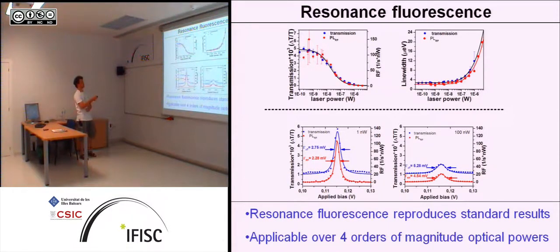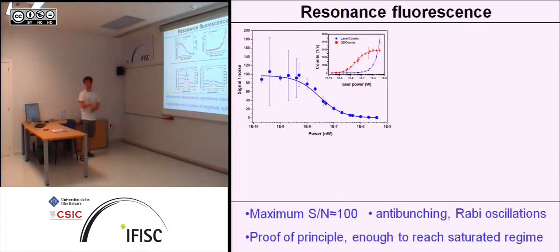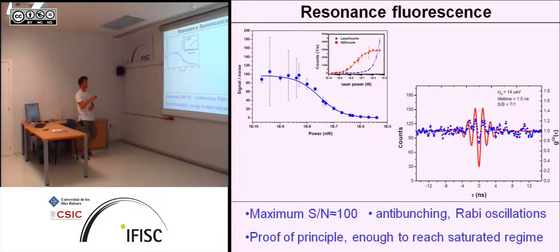And here we now use this resonance fluorescence to basically validate this technique, because the transmission spectroscopy has been around for a few years now, and it's been taken to be a valid experiment. And here we see that basically the resonance fluorescence perfectly, or almost perfectly, reproduces the features measured in standard resonance transmission spectroscopy. And here again 2 example scans showing the power broadening and the saturation of the transition. So this basically is a proof of principle, not more. We use the same results to calculate a signal-to-noise ratio, which is around 100 for unsaturated transition here. And yeah, this is basically the contrast dependency and the collection of laser photons.